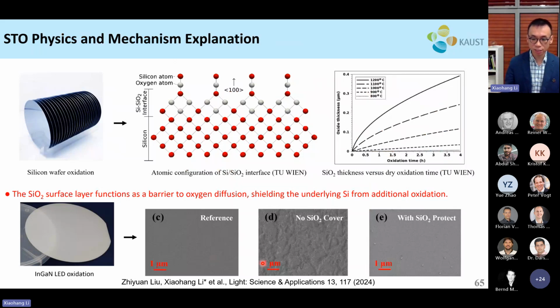So here you can see the surface morphology. This is the surface before any treatment, right? It's just an empty wafer after the growth. This is the area after the oxidation, but it does not have the silicon oxide protection layer. So it becomes very rough because the surface has already been oxidized into gallium oxide, right? It can be Ga2O3, it can be Ga2O2.5, but it's a gallium oxide complex material. So the surface that is protected by the silicon oxide during the annealing still shows a pretty smooth surface.